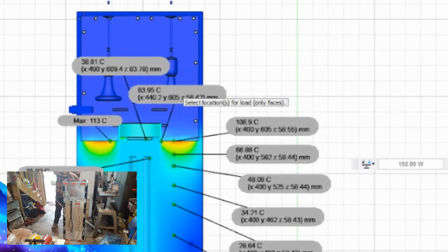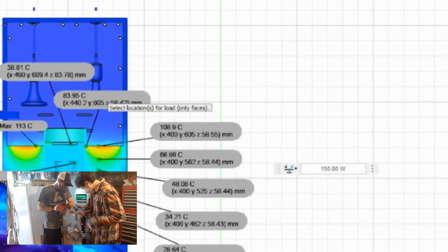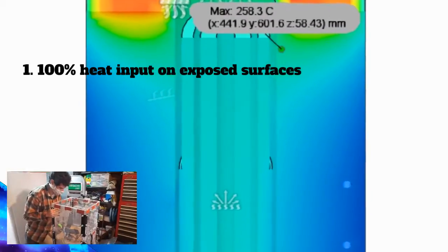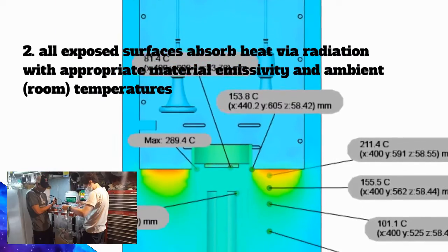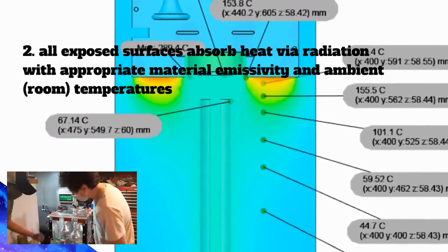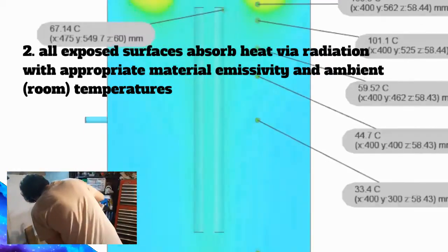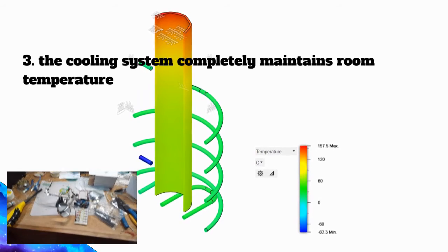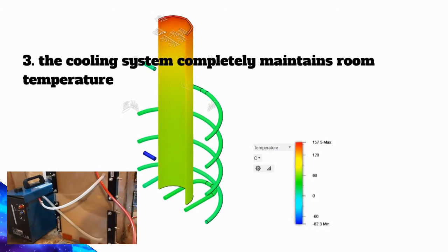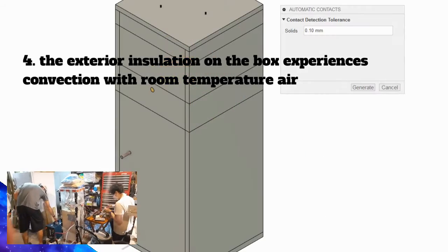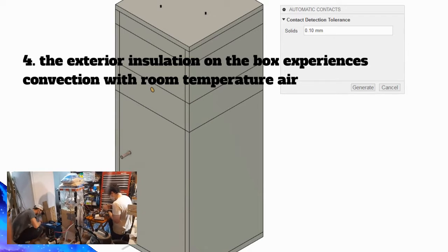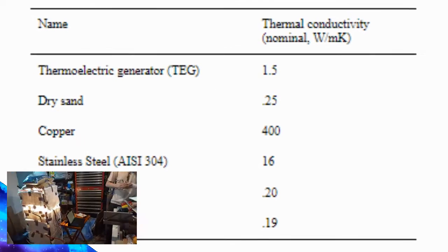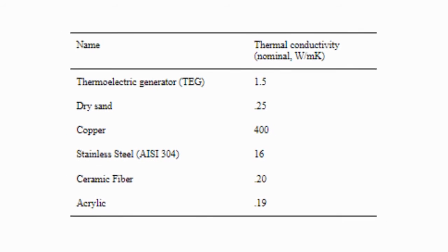This is a very ideal scenario, but these assumptions allowed us to focus on studying the behavior of the mock anchor. The thermal loads on the test rig were as follows. Full heat on exposed surfaces in the plane below the heat lamps. All of those exposed surfaces absorb heat via radiation with appropriate material emissivity and ambient temperature set at room temperature. The cooling system maintains room temperature and may remove unlimited heat to do so, creating a net zero heat in the test rig, and the exterior insulation of the box experiences convection with still room temperature air. All thermal conductivity values are either widely accepted from materials, such as copper or acrylic, or were provided by the manufacturer.